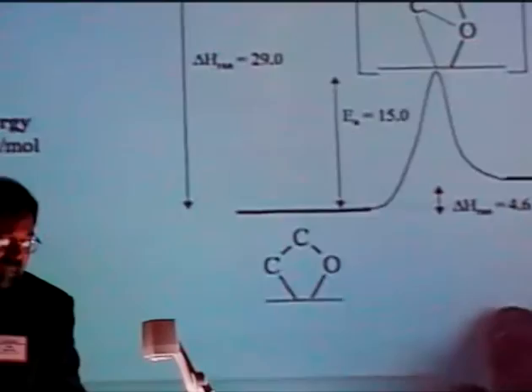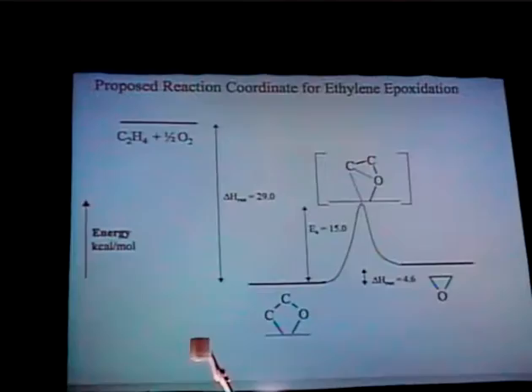So I think there are two key points to be made from this reaction coordinate. One is that for the first time, we have made a stable intermediate on a silver surface in a surface science experiment that ring closes to make ethylene oxide. And I think the other important message is the role of theory in this, because it was theory that basically told us where to look, what temperature window in which we might actually hope to form this by ring opening ethylene oxide.